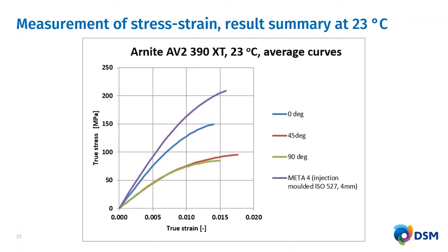And from those measurements, you can see the results here. This particular one is of our PET material. It's 50% glass at the 23°C room temperature, and these curves are averaged. The plaque measurements are these bottom 3 curves here, the blue representing the 0 degree or the flow direction. The cross flow direction being represented by this yellowish curve, and the 45 in the middle, actually fairly close to the 90 degree curve. So I think it's important to note the difference between the flow and the cross flow